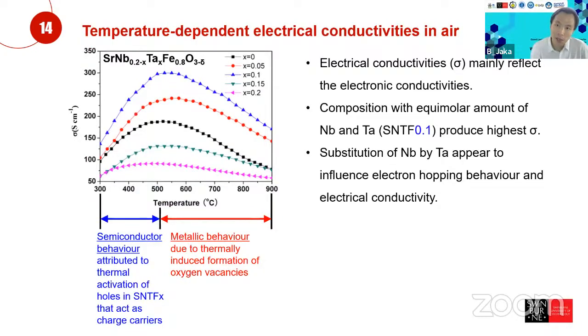Okay, then the next one we check is the temperature dependent electrical conductivities. You can see that we check it as we heat it up from 300 to 900. So we capture two different behaviors in here. The first one is the electrical conductivity increasing with temperature up to around 500, followed by a decrease in the electrical conductivity from 500 to 900. So this can be correlated with semiconductor behavior and metallic behavior. In metallic behavior, the electrical conductivity reduces with increasing temperature. If your material exhibits semiconductor behavior, then it increases with increasing temperature.